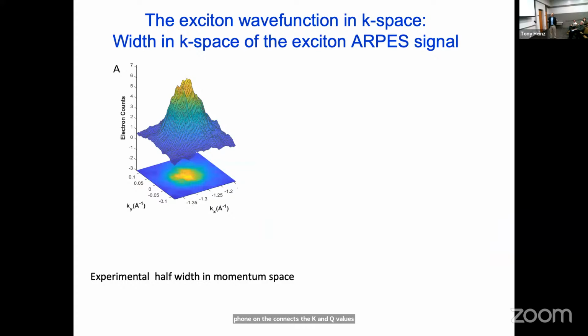Well, let me talk about maybe an even more basic aspect of this. If we just focus on the K-valley signal and we resolve it in momentum space, we find you get some distribution here. It turns out to be 0.07 inverse angstroms in width. And the actual instrumental resolution of the setup was 0.001 inverse angstroms in width. So why do you get a finite width of the distribution of the electrons?